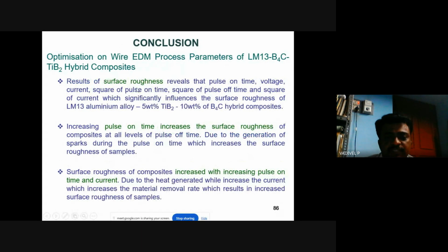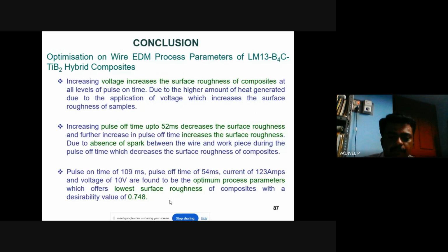When coming to the surface roughness, the parameters like voltage, pulse on, pulse off, and the square of pulse on time give the maximum for the hybrid composites. Increasing the pulse on time increases the surface roughness of the composite at all the levels due to the generation of spark during the pulse on time, which increases the surface roughness of the samples. With the increasing pulse on time and current, the heat generation between the electrode and the surface increases. And here I conclude my presentation, and the session is open to queries.